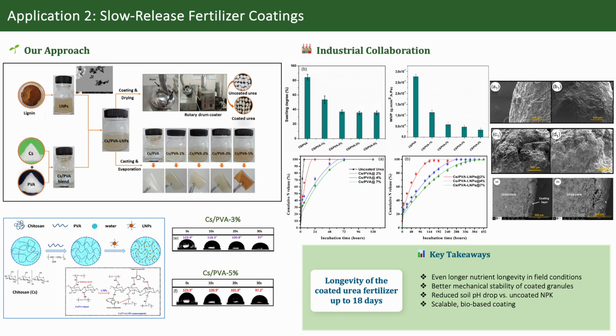The coating strategy relies on the formation of a continuous polymer layer around the granules. This layer acts as a diffusion barrier and controls the contact between water and the fertilizer core. The coated granules showed improved nutrient longevity with the release extended up to around 18 days compared to conventional uncoated fertilizer.